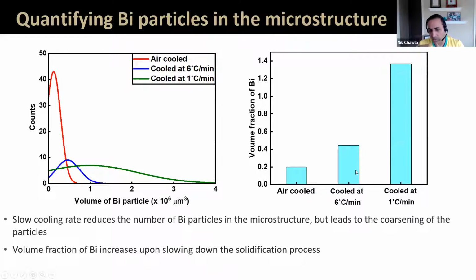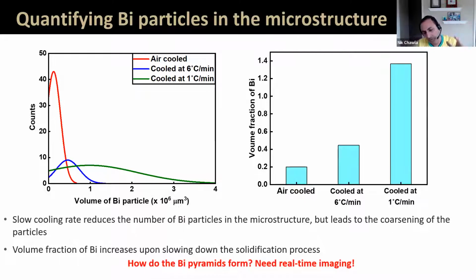The slower you cool, the more time you get for the bismuth to come out, and you get more of this bismuth precipitation going on. But the real question is, how do the bismuth pyramids form? And that's something that we could not really answer using the lab scale technique.